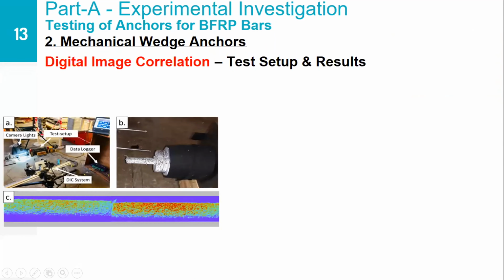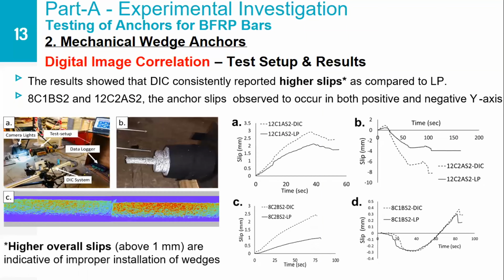Now, as you observed, when we were testing these BFRP bars with the different anchors, there was slipping of these anchors during the test in some of the specimens, because of which some of the linear potentiometers got damaged. Hence, a second measurement technique, the digital image correlation technique, has also been used for some of the specimens, where we applied it at the live end anchor of 4 of the specimens. We observed that the slips recorded by digital image correlation were higher than the slips recorded by the LP, because the LP measures the slip primarily in one direction. However, the 3-dimensional effect is captured by the digital image correlation.